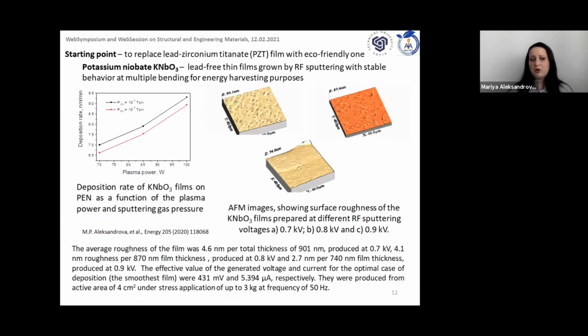So the starting point is how to replace the classical lead zirconium titanate, PZT, with an eco-friendly, lead-free material. And we started with potassium niobate. It is lead-free, could be grown in the form of thin films by radio frequency sputtering in vacuum, and it exhibited stable behavior at multiple bending, which is really favorable for harvesting purposes.